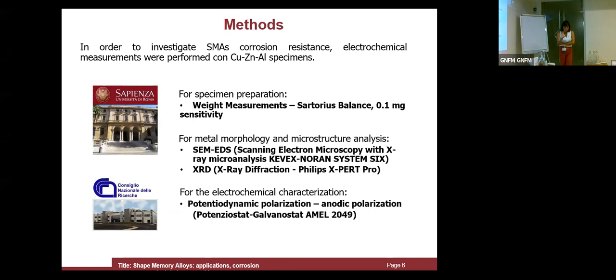From the chemical point of view, we would like to investigate the resistance of this kind of alloy to corrosion. For doing this, we used electrochemical analysis, in particular potentiodynamic polarization curves, and we analyzed the tarnish product developed on the surface using two really well-known techniques. Scanning electron microscopy with X-ray microanalysis in order to detect and analyze the metal morphology, and XRD diffraction for the microstructure analysis, for the crystallographic identification of our samples.